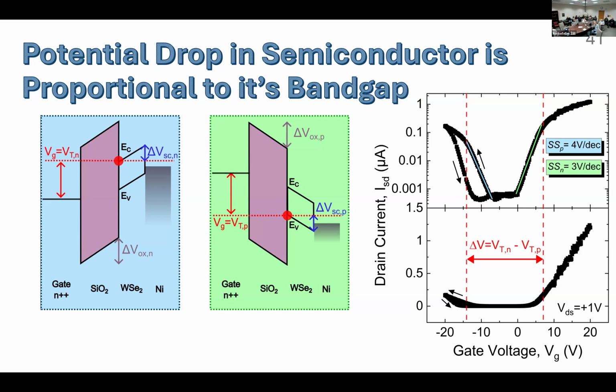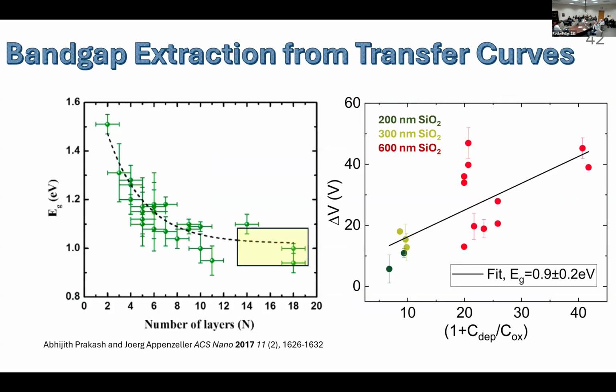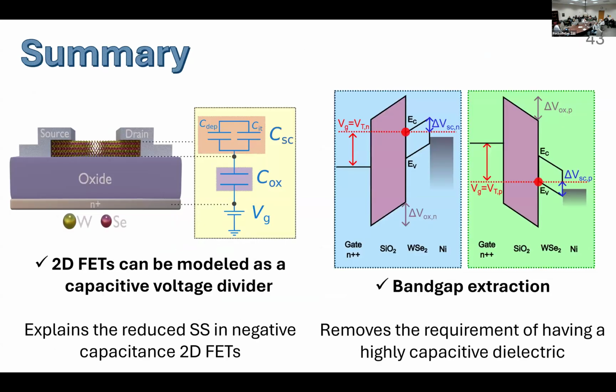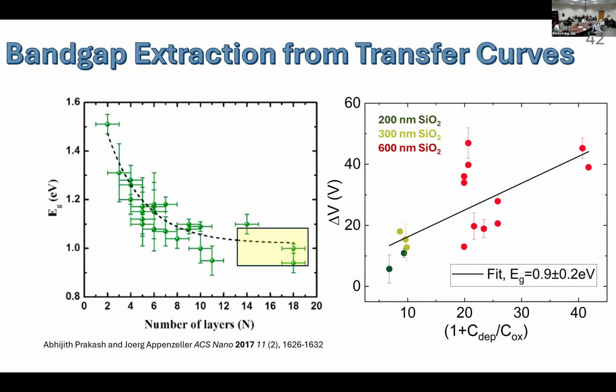And so by simply taking the difference between these threshold voltages and taking into account the geometric configuration of the thickness of the semiconductor and the oxide, we can find a value for the band gap of our tungsten diselenide flakes. So simply by plotting this shift in the threshold voltage as a function of the depletion capacitance and oxide capacitance, we can obtain a value for the band gap, which is approximately 0.9 eV, which is similar to the band gap values obtained experimentally in tungsten diselenide devices.